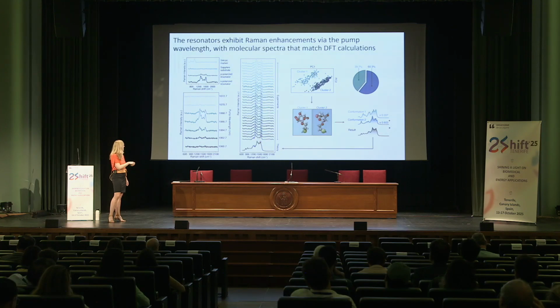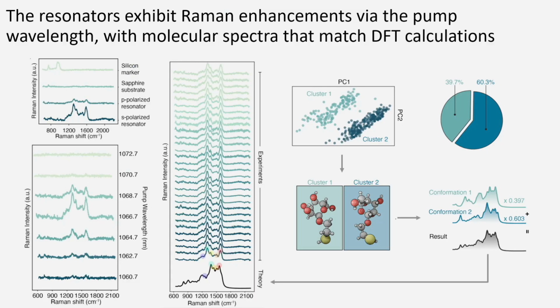But here for this particular sugar, when we collect the Raman spectra, what we do is figure out what are the different conformations, and then how do those conformations give rise to different Raman scattering signals. For this particular sugar molecule, you can see that there's actually 2 different conformations, here shown as those 2 different clusters. And when we're doing these dynamic calculations, we can see that one of the clusters, that conformation, is present about 40% of the time, 39.7% of the time.